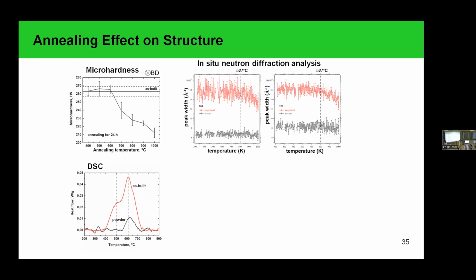Also, differential scanning calorimetry demonstrated an endothermic peak, which starts from 400 degrees Celsius, and other peaks in the middle, around 500 and 600 degrees Celsius. The beginning of the peaks is associated with the beginning of the movement of point defects. We also observed the result of in situ neutron diffraction analysis, which demonstrated that the peak width of the as-printed material, the red dots, decreases starting from a temperature of 800 Kelvin, which is about 530 degrees Celsius. This is associated with the relaxation or recovery process of the material, where the dislocations start moving.